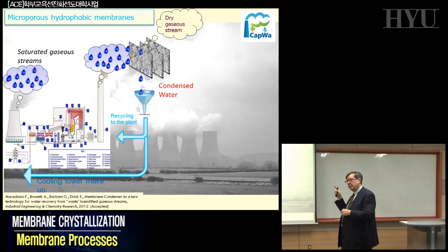And also here, as we learned, you can have more than just crystals or evaporation, you can have specific crystals, etc. When you start to work on this, you can have a new kind of condenser in which you can control, for example, the level of contaminants. Because what is coming out from here is not just water. It's water plus, depending on which kind of production you have, fluoridic acid or ammonia or sodium sulfate, depending on the kind of industry, textile, pulp and paper, etc. And keeping control of the quality using the traditional technology is not easy and complicated, to the point that people normally are not doing it. With a membrane system, by understanding the mechanism and controlling the system, you can condense water with no fluoridic acid, or water full of fluoridic acid, in such a way that you know what to do to reuse it, to use it in another part, etc.